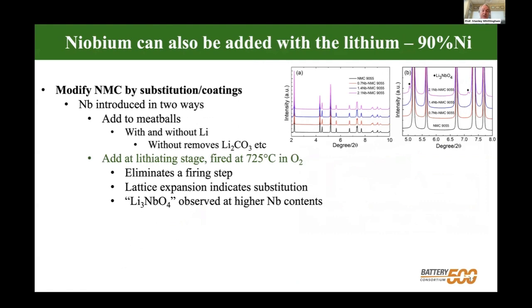And in this case, if we heat to higher temperature, what we did here was use the same lithium niobium ethoxides, soak the meatballs in it, and we get perfect solid solution in here, and no surface species to speak of until we get to very high niobium concentrations. The lattice just changed in size, so it's getting solid solutions. And you can see at 2%, we're getting a second phase, and maybe a little bit here, but nothing at the 1% or less. And the phase we are observing at higher niobium contents is Li3NbO4.